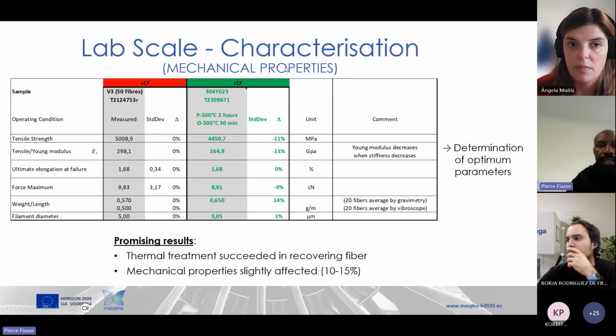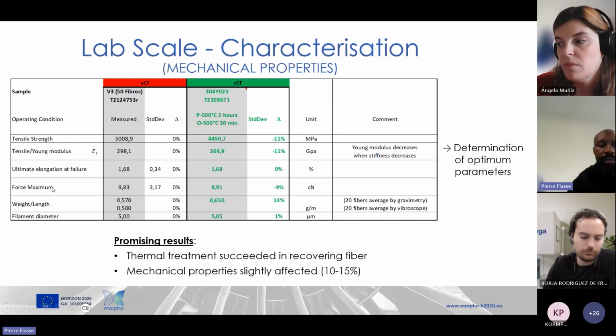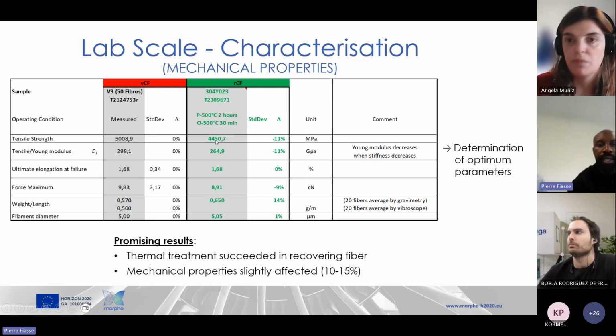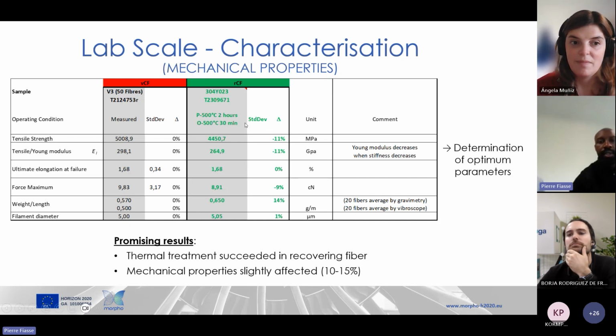So this one is a table with the mechanical properties of the fiber. On the red one, we can see the virgin properties for different parameters like tensile strength, Young modulus, ultimate elongation, maximum force, and so on. And for the green one, we can see the data we get for the recovered carbon fiber with the parameters we chose, so 2 hours of pyrolysis and 30 minutes of oxidation. That is clearly a success for us because we get recovered fiber with only 10 to 15% loss of properties compared to the virgin one. So that is really a good thing for us.